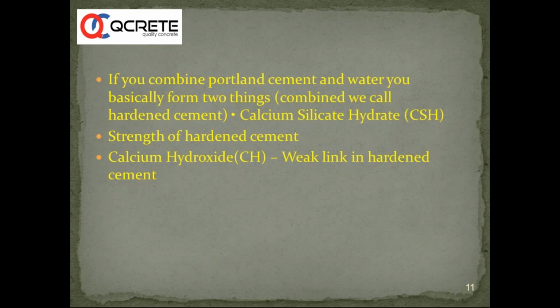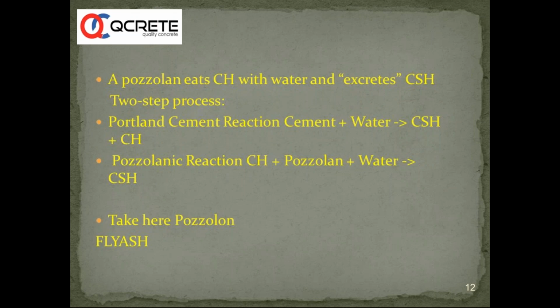So when we reduce the usage of OPC, you have a reduction in calcium hydroxide. To make calcium hydroxide react with another material to make a more stable CSH gel, more CSH gel and a lesser amount of calcium hydroxide, you need SiO2, and that SiO2 is fed from pozzolanic materials like fly ash. So Portland cement reaction: cement plus water gives CSH plus CH. Pozzolanic reaction: CH plus pozzolan plus water. It will lead to more CSH gel, denser concrete, stronger concrete, and of course you will be left with some amount of calcium hydroxide.